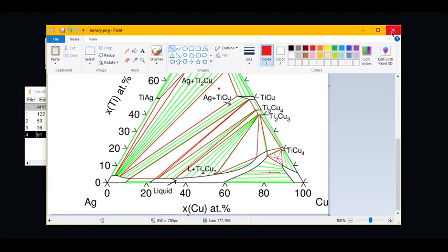So suppose we're in the two-phase region here, meaning it's a mixture of the liquid phase and the copper phase. When I say phase amounts, I mean what percentage of that mixture is copper and what percentage is liquid. When we say phase compositions, it means what percentage of a particular phase is composed of a particular component.